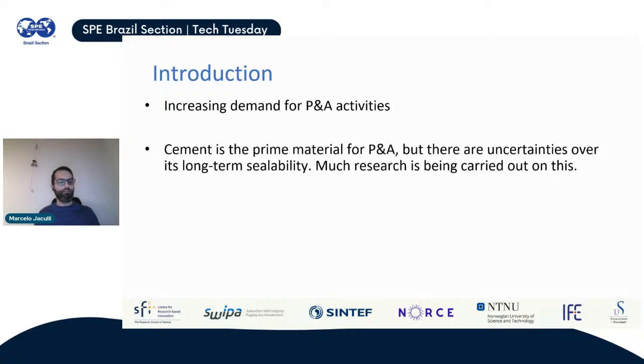The problem that has been posed to us is that since we only have cement as the prime material for P&A, and there are all these other initiatives for alternative materials, we actually need to test them, because there are concerns about whether cement will be able to hold its long-term sealability. There is a lot of research being done about cement itself, how to improve the integrity of wells abandoned with cement, and how to improve cementing job quality. But at the same time, we should also be looking for other potential materials that could work as a replacement for cement or even in combination with cement. So that's where bismuth comes from.